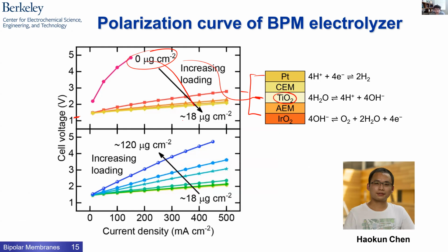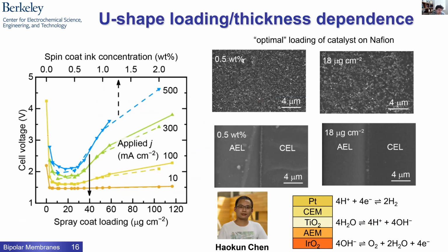The cell gets much, much better. As you would expect, more catalyst, faster reaction. But then you put too much catalyst in and it gets bad again. So you get these U-shaped curves with the amount of catalyst and the cell voltage.